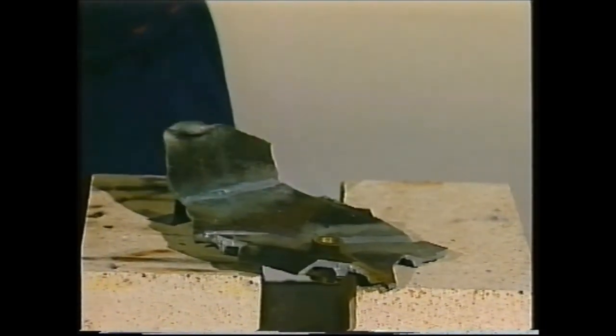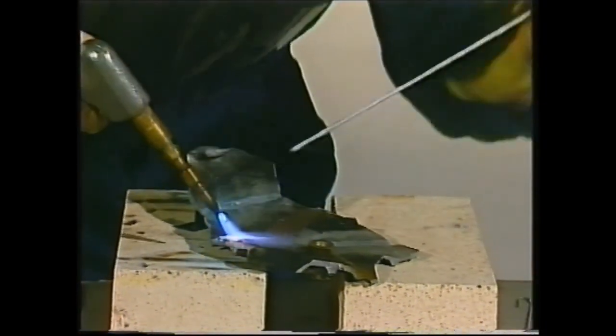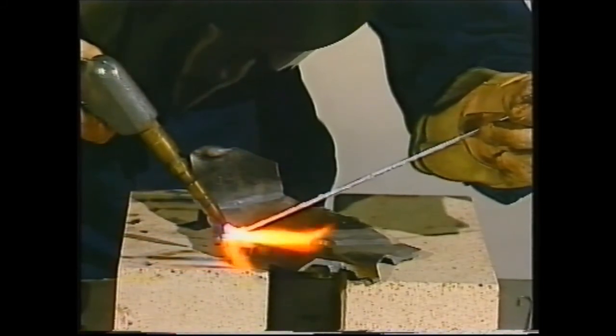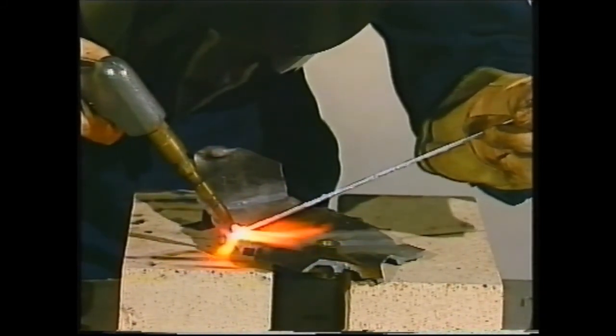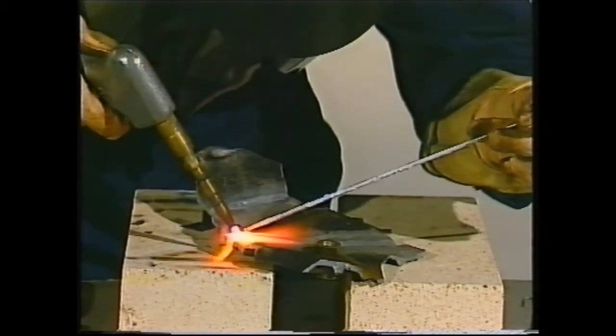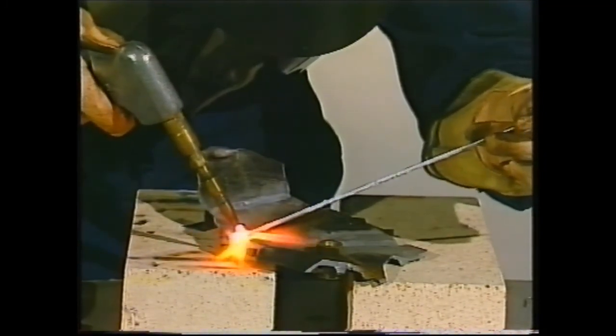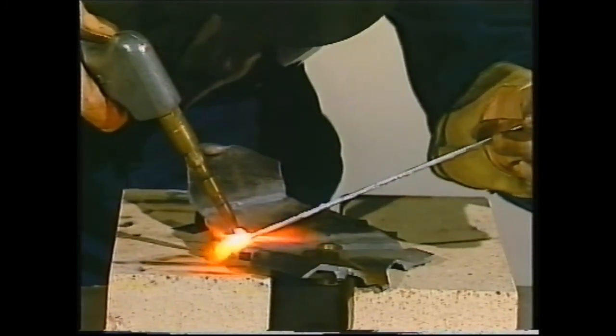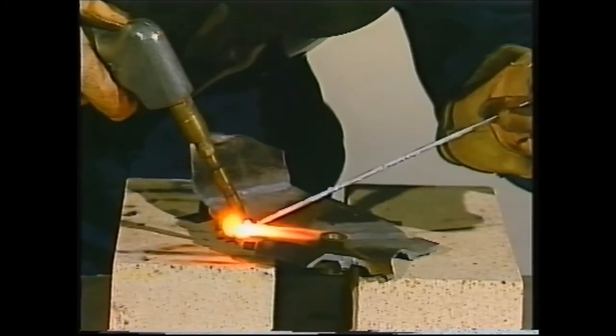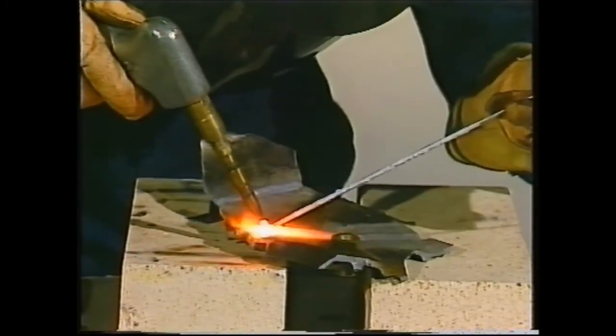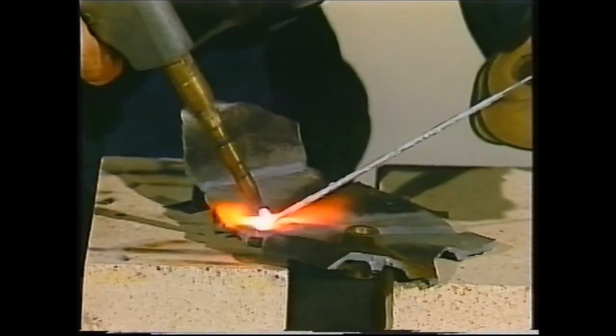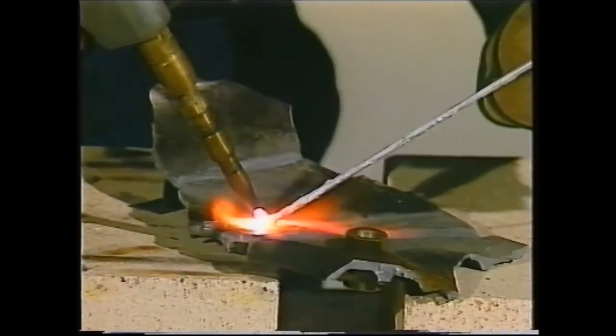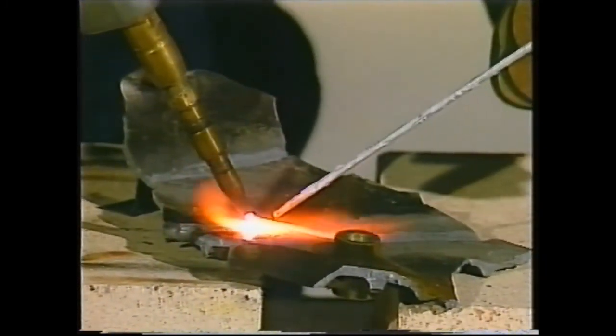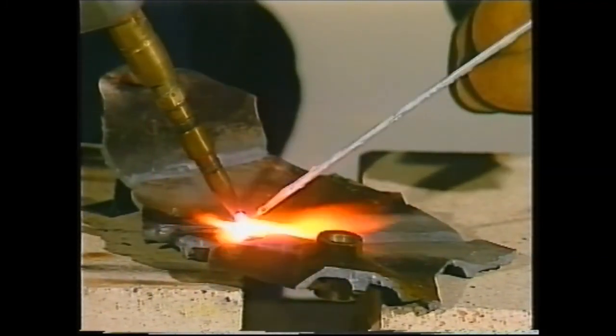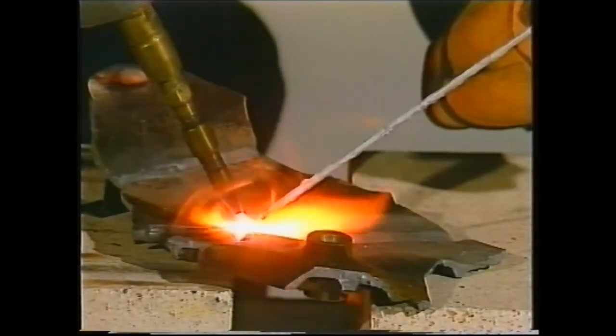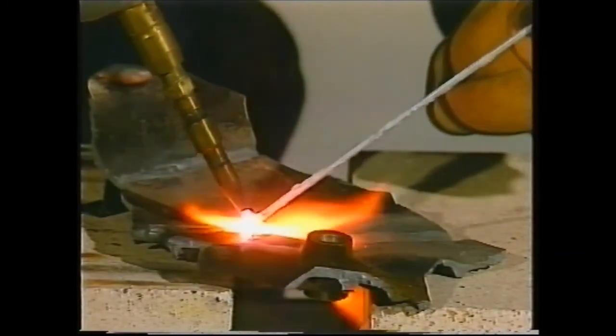This is just standard 4043 filler rod, as I said. Very inexpensive rod. And again, you notice that technique with the torch 20 degrees off vertical and the rod going under and out of the way of the flame as it goes across. The cone of the flame's held about a 1/16 of an inch above the work. But unlike a conventional torch again, you don't have to pull it away, and it does not, as you can see, collapse the material away. It makes it very, very simple to weld even the thinnest cast aluminium.